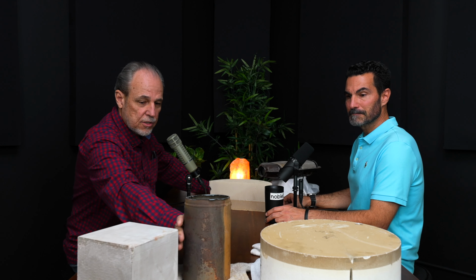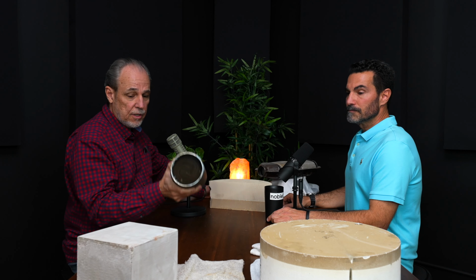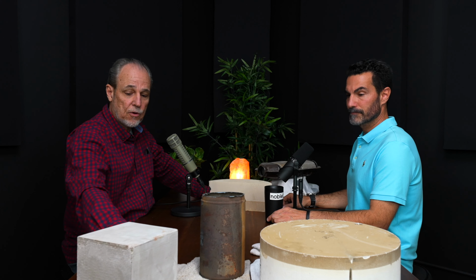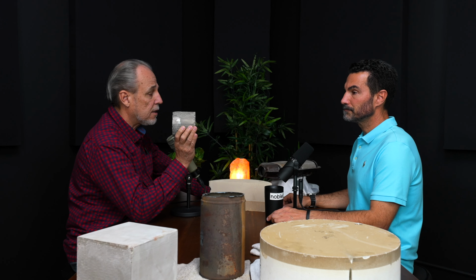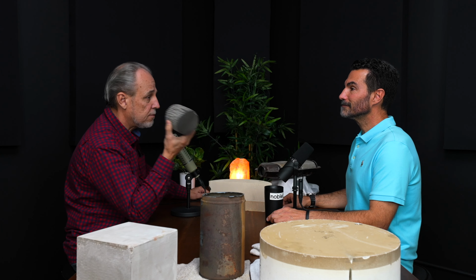And then now we have other issues that the pyrometallurgical process can't handle. One is, say, a foil converter. This is a foil converter here. Rolled steel internally, right? And this has wash coat that's hosted on the surface of the rolled steel. This has to be mechanically shredded, air separated to recover the powder. The powder has the precious metal. That can be introduced into the furnace. But you can't take this monolith from a rolled steel converter and go straight into the furnace with it. You've got to pre-shred, air separate, collect the powder. I've got a bag of powder in the lab from this process, right?